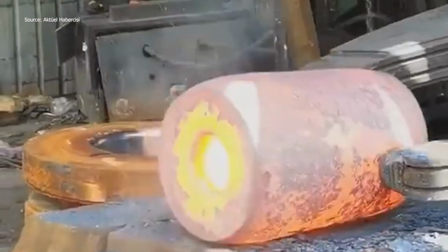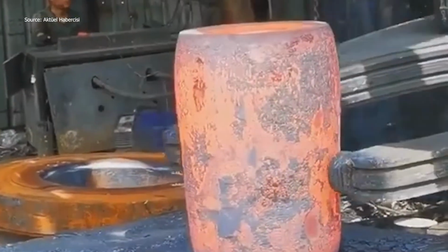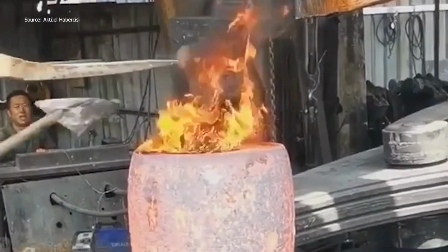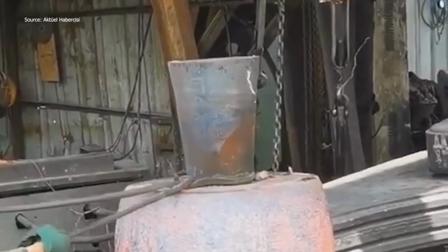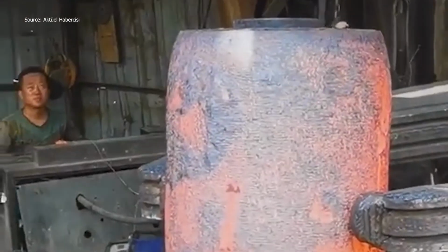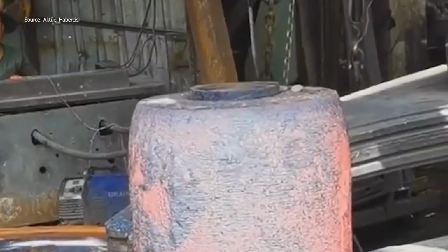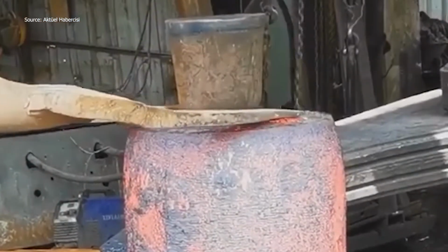Hot forging involves heating steel to approximately 950 to 1,250 degrees Celsius for carbon types, or 1,095 to 1,150 degrees Celsius for stainless. Once heated, billets are shaped using mechanical or hydraulic presses, applying up to 160 meganewtons of force at speeds reaching 50 strokes per minute. Automated lines can deliver 90 to 180 pieces per minute, depending on billet size.